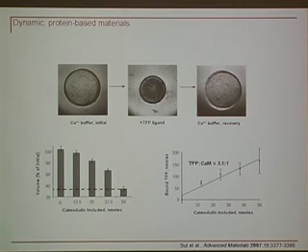So you can actually see that as the ligand diffuses out, we get recovery of the initial volume of these hydrogels. And as we vary the amount of Calmodulin included into the gels, we can vary the degree of volume shift of the materials. So for engineering purposes, this is an important result. So we get as much as about a threefold decrease in volume on the high end, which for bioresponsive materials is pretty positive. So we're enthusiastic about this.